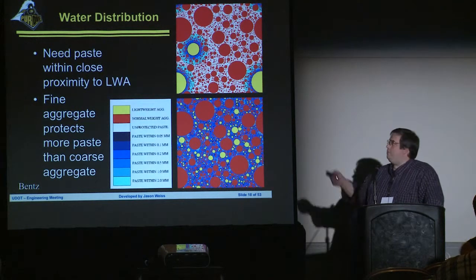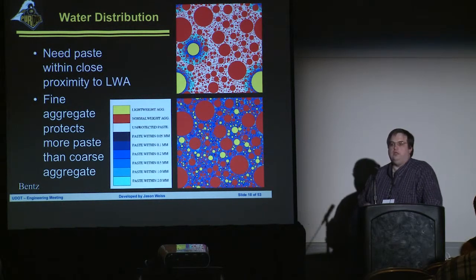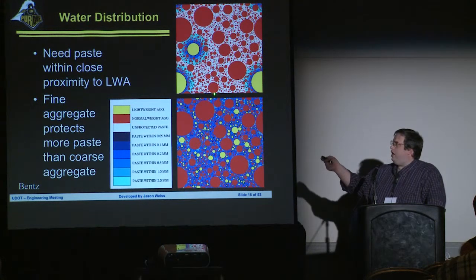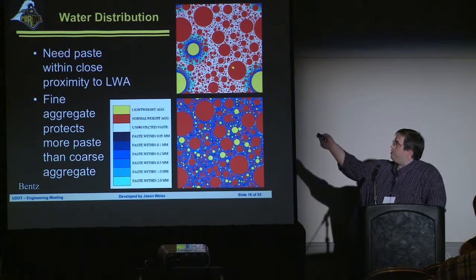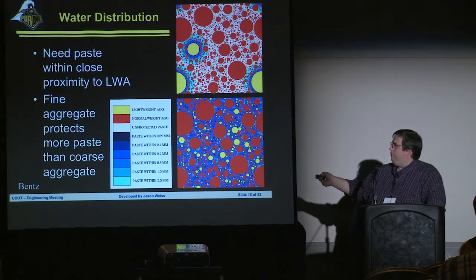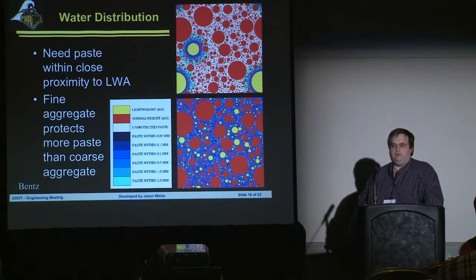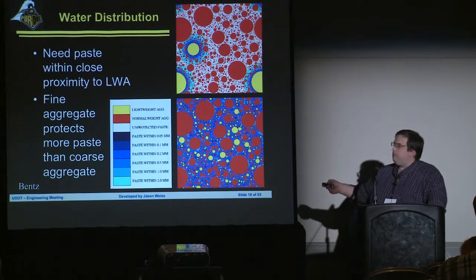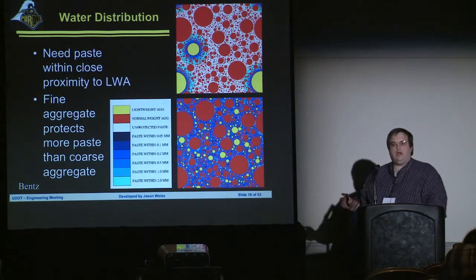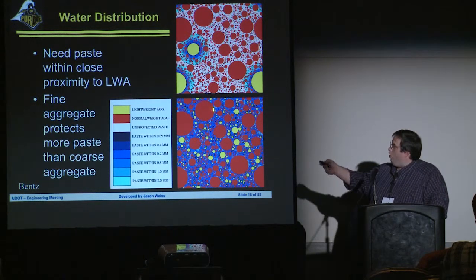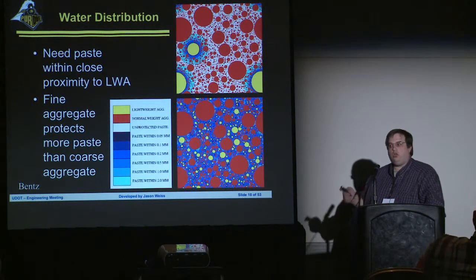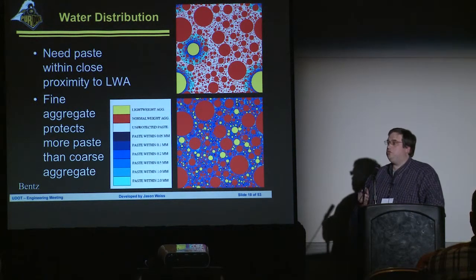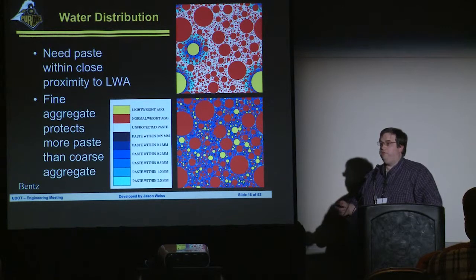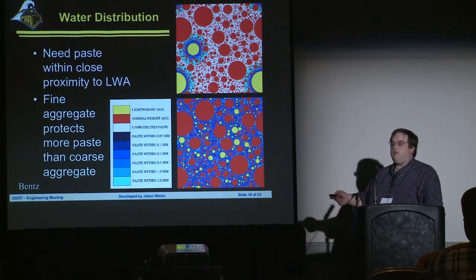The only difference between the top picture and the bottom picture is the size of the lightweight aggregate. They have exactly the same volume of lightweight aggregate. This is a coarse lightweight aggregate up here. This is a fine lightweight aggregate down here. The whole goal to making this work is you want to have these lightweight aggregates distributed throughout the system so that all of this paste is very, very close to an aggregate. Because remember, water can't travel that far. Typically, water can only travel about 2 millimeters.